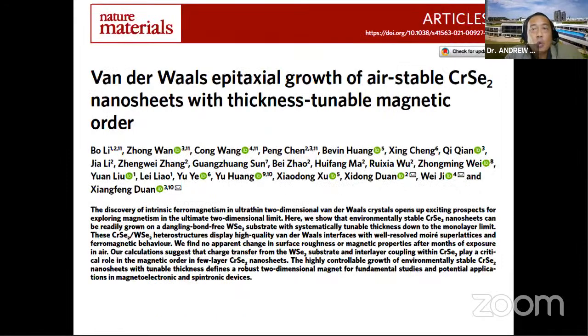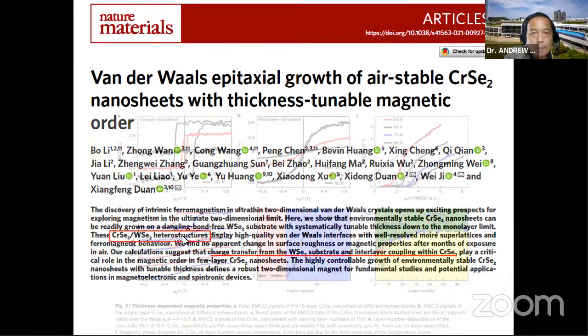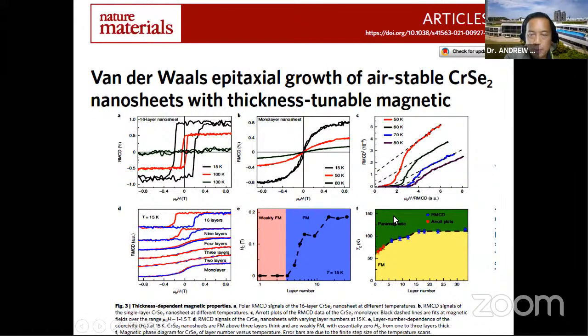dichalcogenide compound, right? So this is some prior work on chromium selenide nanosheets done by this UCLA group, and they showed ferromagnetism. In fact, they specifically studied chromium diselenide on tungsten diselenide heterostructures. The main result is that charge transfer with the tungsten diselenide, as well as interlayer coupling with this chromium diselenide, play a critical role in the magnetic order. So while they show that these chromium selenide 2D compounds are magnetic, the interface plays an important role. And these are some of the results where they showed layer-dependent magnetism, and they mapped out the phase transition space of the material. So it's an interesting material that has potential applications.